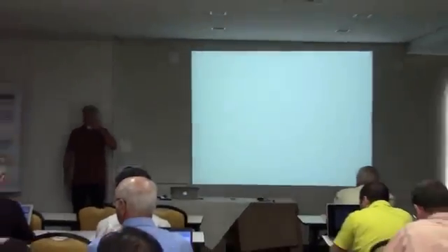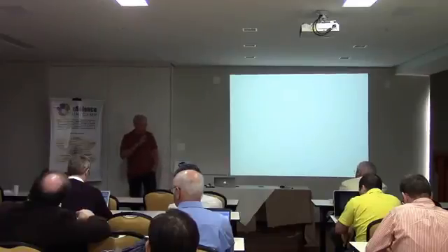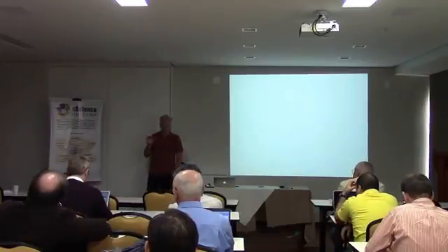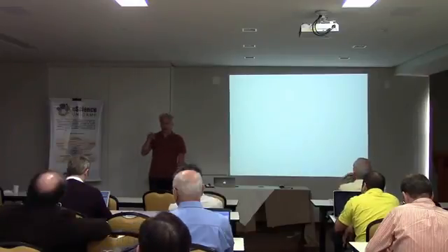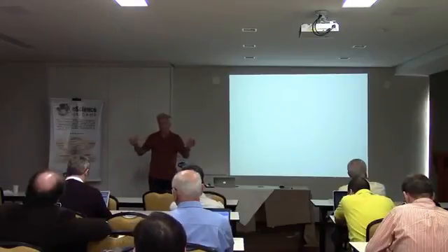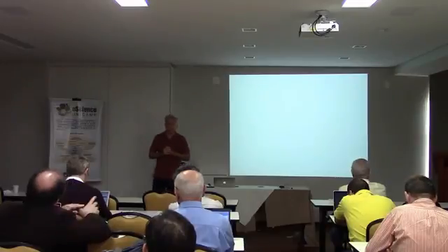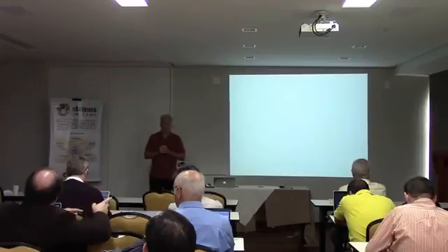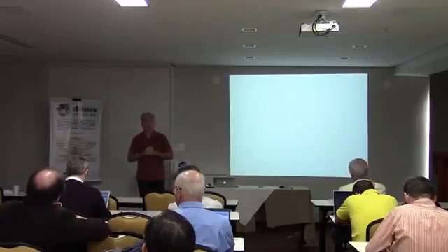For the nanoparticle experiments, at what voltage, low voltage, high voltage? I don't remember exactly all the voltages, but they performed also a study looking at the dependence with the voltage. So it's for a very broad range of voltages, and the result is independent of the voltage. But do you know if at high voltage the electron beam has enough kinetic energy to sputter the sample or not? No. It's below the threshold.